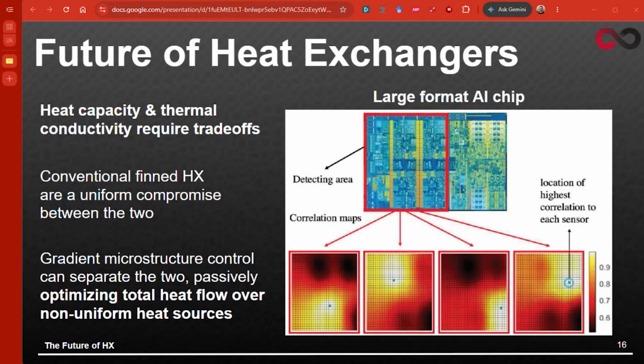From Jeremy, we have: have you looked at radiative cooling, not just conductive? Radiative cooling generally involves higher temperatures for it to compete with conductive or convective solutions. For our bare copper solutions, generally when we start to heat them to the point where radiative cooling becomes substantial, they start to oxidize in air. So we do need to do some passivation work, basically cover the metal with a very thin layer such that when we really get them hot, like glowing hot, they don't oxidize, which of course impacts the experimental results. So radiative cooling is something that we've just touched the surface of in terms of R&D, but I'm very interested to look more into those numbers later.